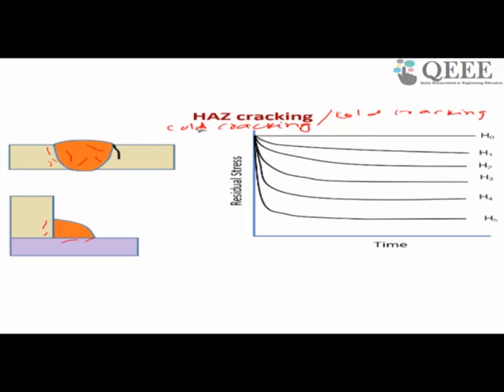Why does it happen? It happens after a long time. When you do welding, it may happen after 1 week or 1 month or 1 year of the completion of welding. It happens because of hydrogen. This is also called hydrogen embrittlement. As we have already discussed from the phase diagram, hydrogen has very high solubility at high temperature, but very low solubility at low temperature.